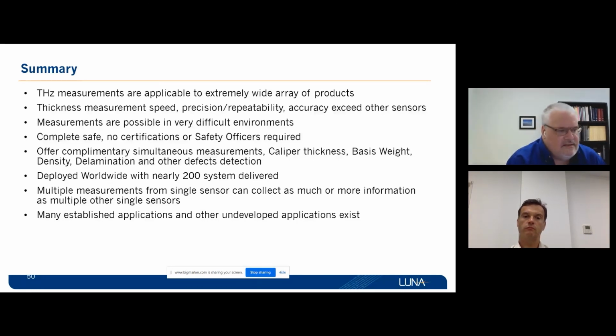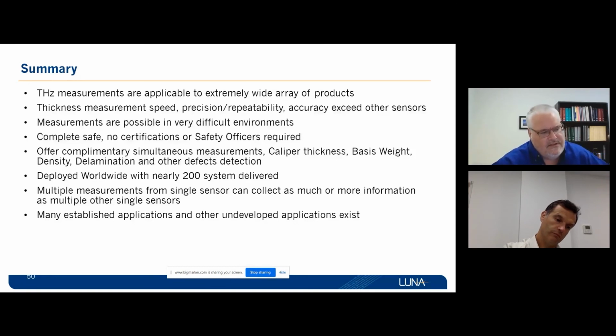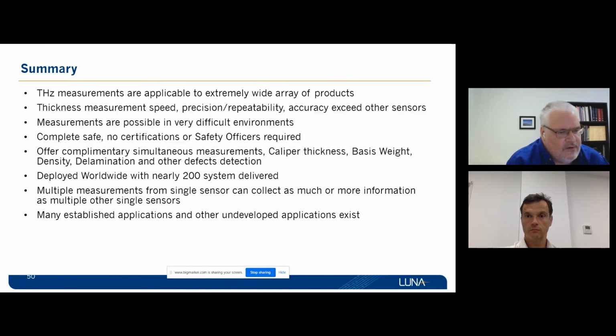So this system can measure thickness, or sort of the phase, down to about 10,000ths of a wavelength. So you can measure the total thickness of something thick very precisely compared to the wavelength. The next thing is, now suppose I have one layer and it's getting smaller and smaller. What's the minimum layer thickness I can measure at once? That depends on the total bandwidth of the system that penetrates through. If we have between, say, 50 gigahertz and 3,000 gigahertz, then you are measuring with nearly 3,000 total gigahertz worth of bandwidth at once. Thinking of it in a Fourier way, the total bandwidth then depends on your thickness resolution.